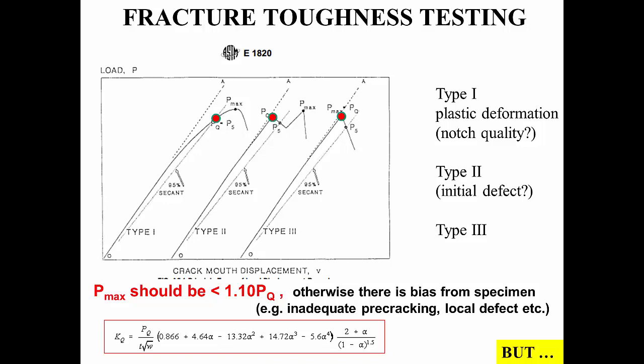So when it comes to testing a fracture toughness specimen, we obtain from the testing machine a plot of the load versus the crosshead displacement. Sometimes, instead of load versus crosshead displacement, it's more accurate to plot the load versus what's called the crack mouth displacement.